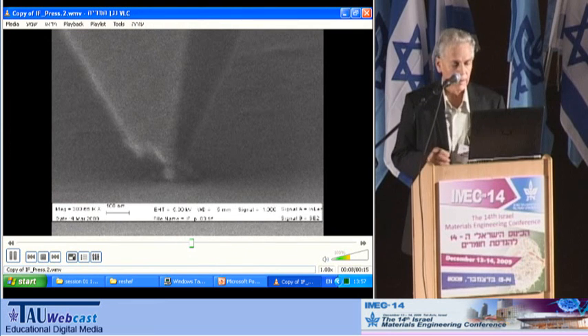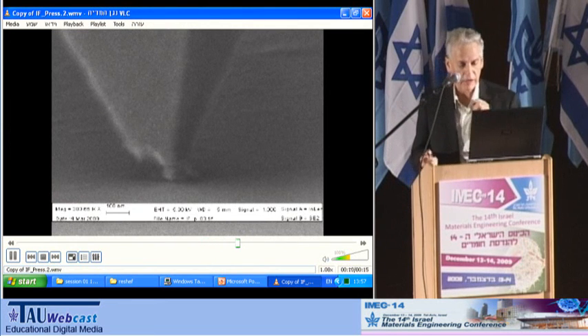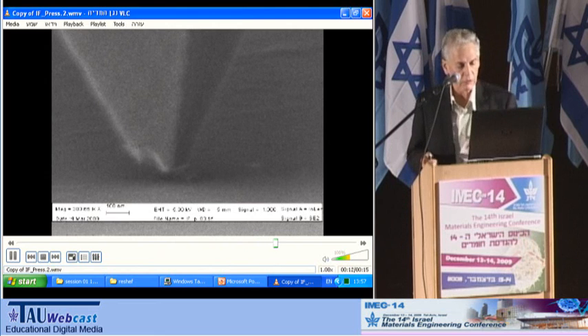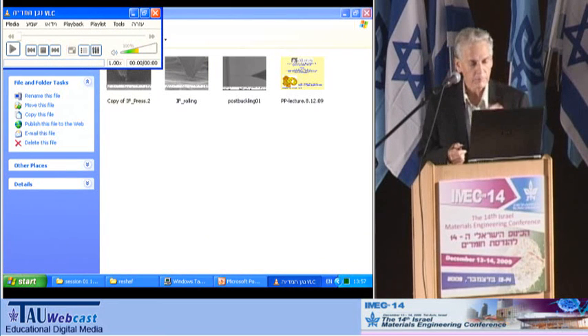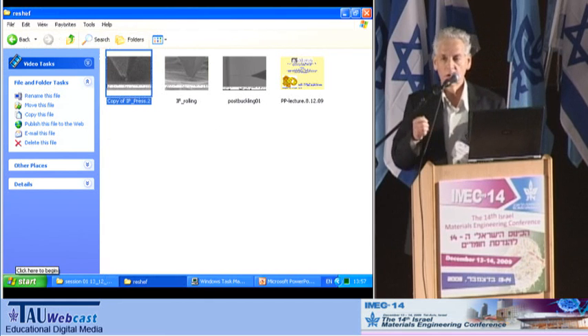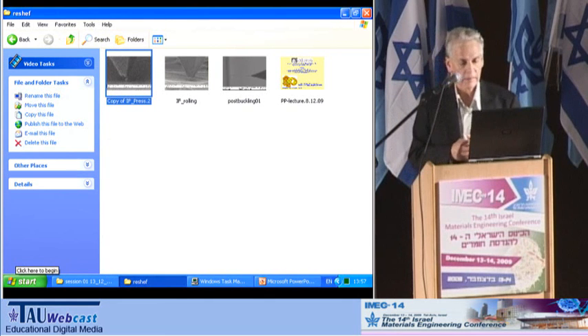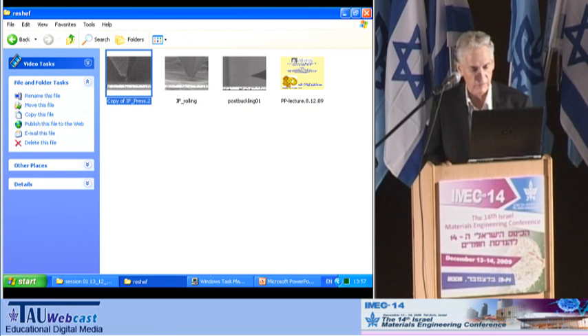So you see the AFM cantilever within the electron microscope compresses the nanoparticles until the nanoparticles break down. And in this case, the force, or the load, that you have to apply is about 3 gigapascal, which means that the nanoparticles are extremely robust against failure.